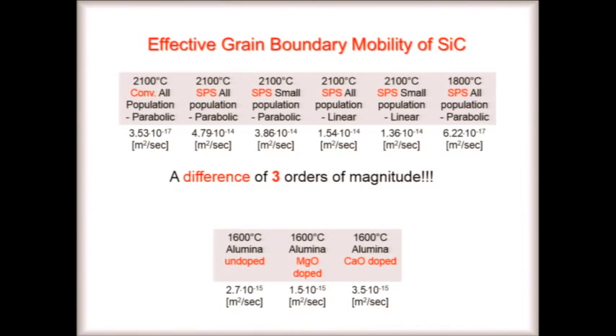This is silicon carbide up top. On the far left, conventional annealing, and this is the mobility. 3 times 10 to the minus 17, that's what I showed you before. This is SPS, a 3 orders of magnitude jump in grain boundary mobility, and these are the different fits, you know, parabolic or linear, only the small grains, all the grains. One can argue, but it doesn't change the end result, that when you put on this external field, the grain boundaries move extremely fast.